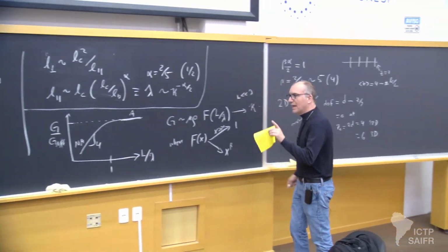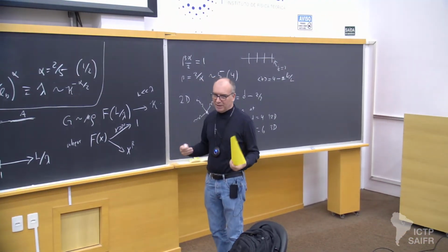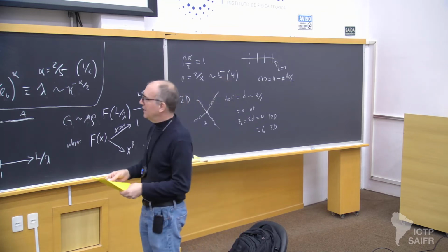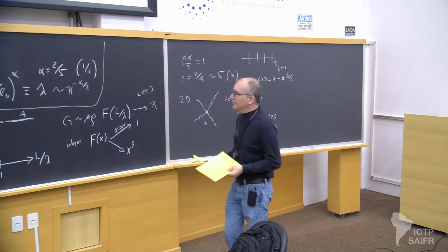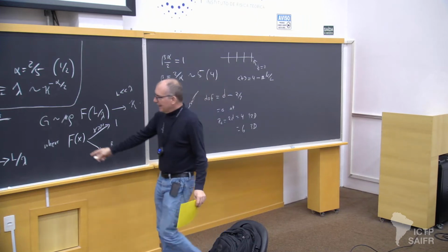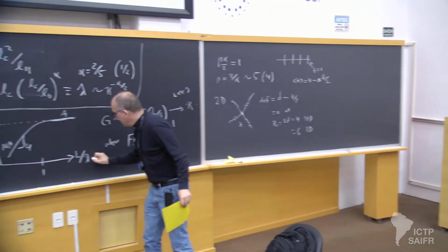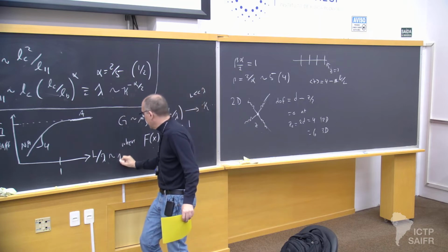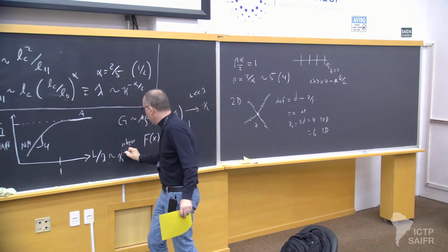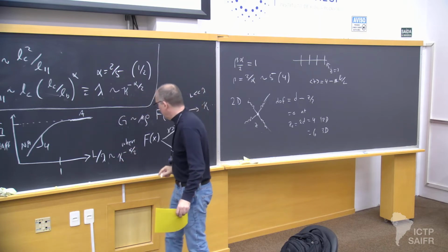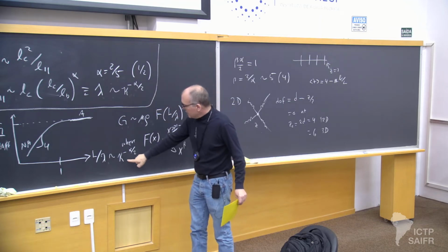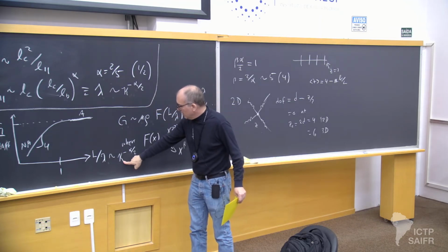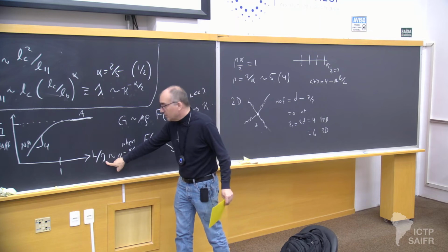Okay, so here's what's happening. And here's why we strongly believe that this should apply in 3D. What does this say about Maxwell? Well, notice this goes inversely in lambda. Lambda, I've just said, goes like kappa to the minus alpha over 2. Notice that as kappa goes to 0, this length, lambda, diverges.